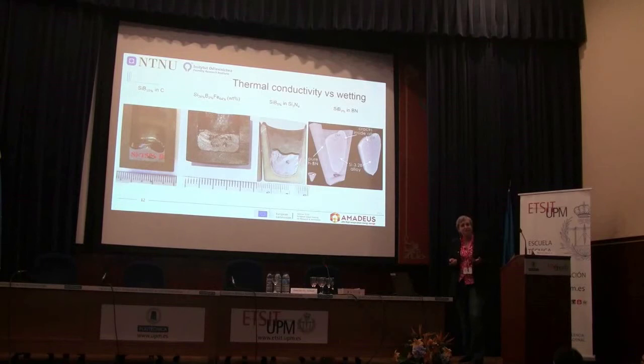I would guess that maybe this is not a big problem when you have a big crucible like we have in the prototype, but that we need to investigate. Another thing is about the wetting, especially for silicon. If silicon wets very well when it's in liquid state, it will have a tendency to creep. It's not very easy to see here, but you can see that the silicon is creeping up on the crucible, and it can actually go over the edge if it's too wetting.